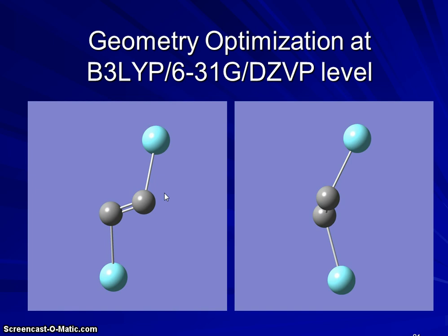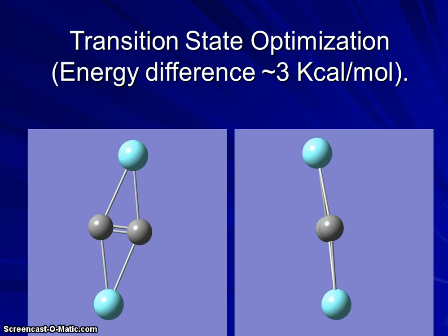So we reran these several times, and what we found is that the expected structure based on the NMR and based on Alan Balch's X-ray of the gadolinium version is not the optimized structure, but it's a transition state between two optimized structures with an energy difference between the transition state and the optimized structure that's fairly small, 3 kilocalories per mole.